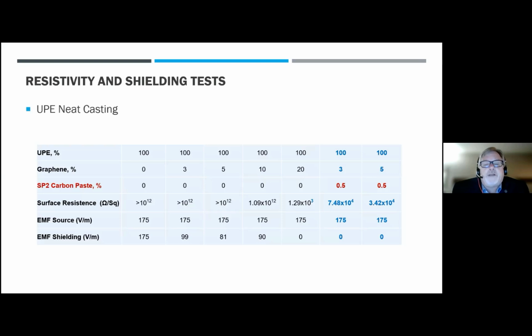If you go up to the 5% graphene level, it drops down to 81. Again, on the equipment that we're using for measuring surface resistance, you're not seeing anything that's less than 10 to the 12. So go all the way up to 10% and then 20% graphene, you could start to see the surface resistance dropping. You see it where we can measure it at 1.09 times 10 to the 12th. And then on the 20% level, you're seeing quite a significant drop. So from the 10% level to 20% level, all of a sudden, the graphene is really contributing to adding conductivity to this neat casting, and you're seeing that it's actually doing absolute shielding as well. Whereas at the 10% level, it's still not. You're getting poor shielding, going from 175 down to 90, but at 20% level, you're seeing absolutely good shielding,